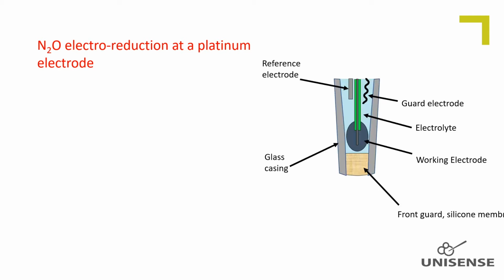It consists of a nitrous oxide sensitive amperometric microsensor which is built like other Unisense amperometric microsensors, with a glass casing equipped with a silicone membrane, working electrode, reference electrode, guard electrode and electrolyte. The negatively polarized working electrode is made of platinum, which has a nitrous oxide reduction catalytic property. The electrolyte consists of an organic solvent containing a suitable salt, ensuring electrical contact between electrodes and charge balance. The guard electrode consumes oxygen and other substances dissolved in the electrolyte, which would otherwise react on the working electrode. So the guard electrode keeps the baseline low. The reference is a silver wire.